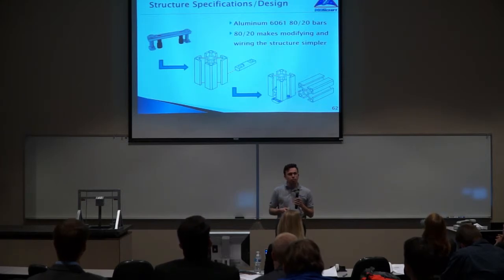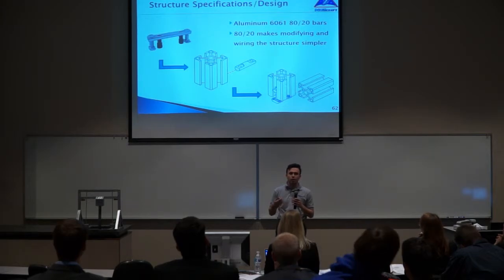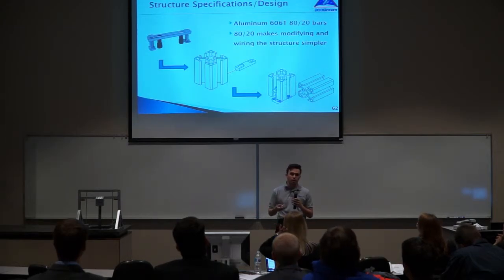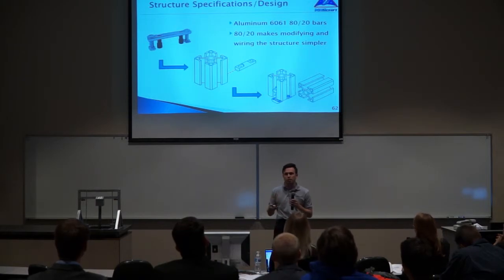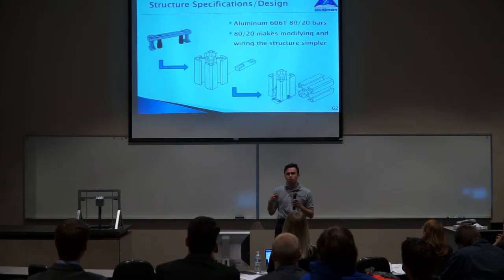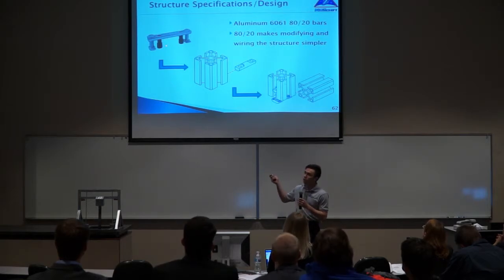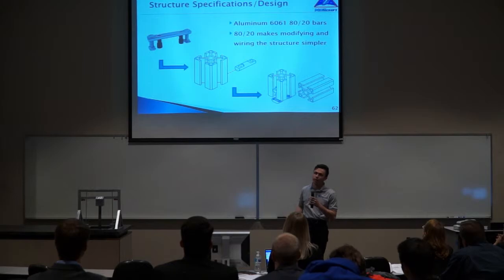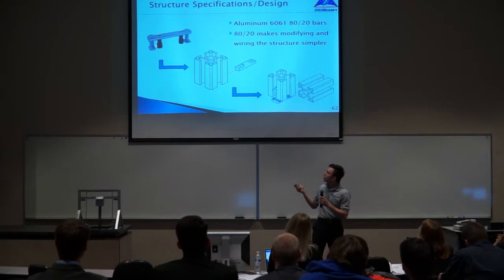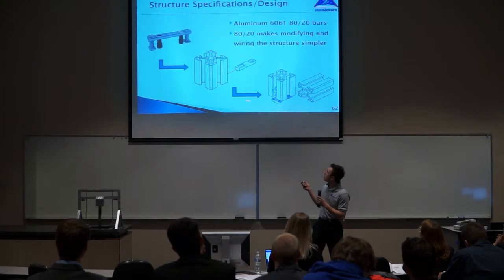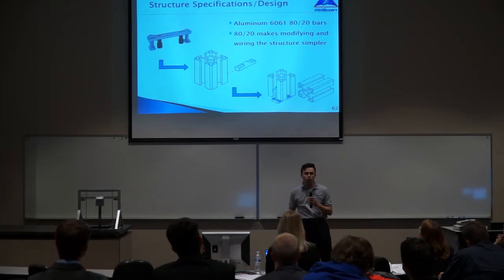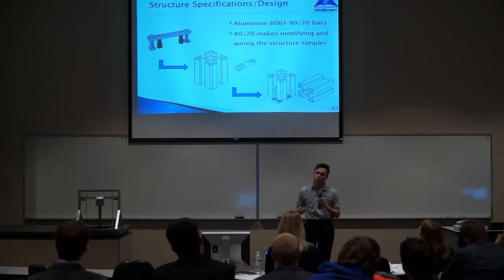As far as materials are concerned, we had chosen aluminum 6061 80/20 bars. The rationale is that 80/20 in and of itself is cheaper than round stock or square tube, and it also has an intense amount of modification applications. As you can see in this picture, this is just one of many. The 80/20 company offers about 3,000 fastener types for their modifications. It's a very simple bar as well as an adjustable screw setup. You would have a hole in this 80/20 aluminum stock, place the screw through and adjust whatever tightness you need to another aluminum stock. It would also make wiring the structure significantly easier due to the channels within it.